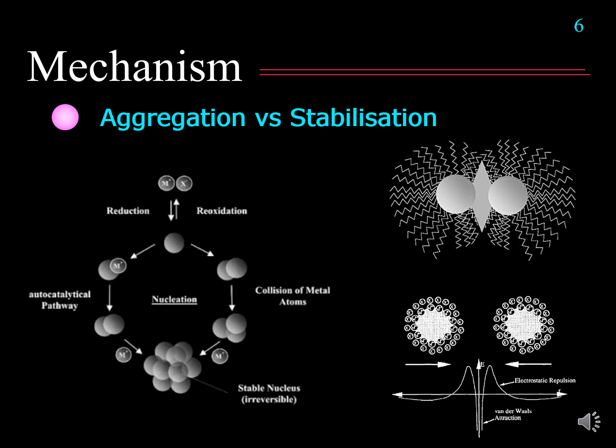So in this case of the citrate, normally the excess amount of sodium citrate can absorb on the surface of the gold nanoparticles. So now the surface of the gold is covered by the anion of citrate. So with the anion negative charge, we can have the electrostatic repulsive force, preventing them from aggregation.